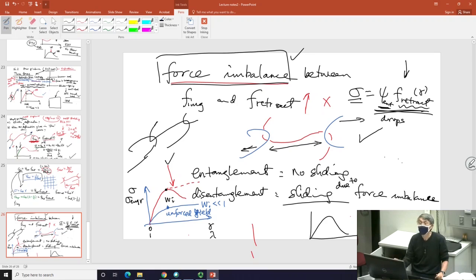This only depicts the ones that have not reached force balance, so they will still further stretch. So this is still monotonically growing. And then you know the answer for the total: this must drop. Why? Because you're losing the density, the effective strands that are still there. So this thing is dropping.